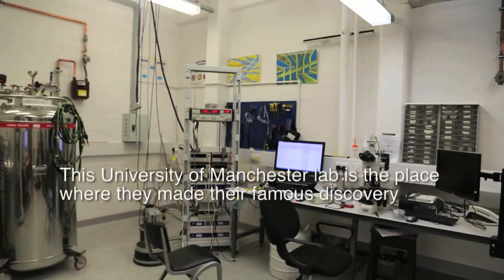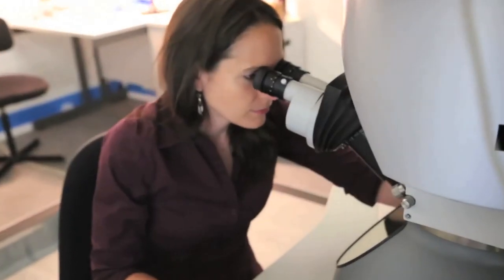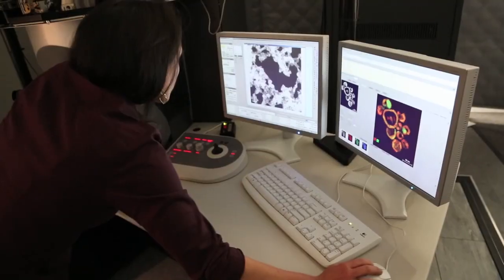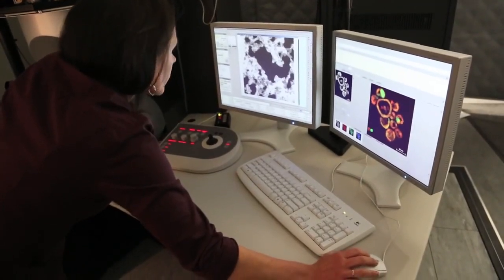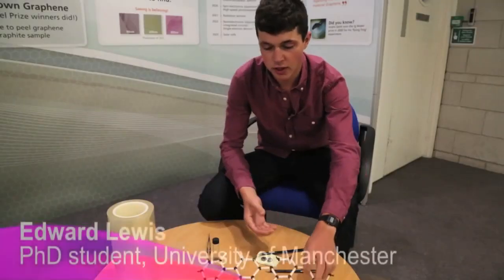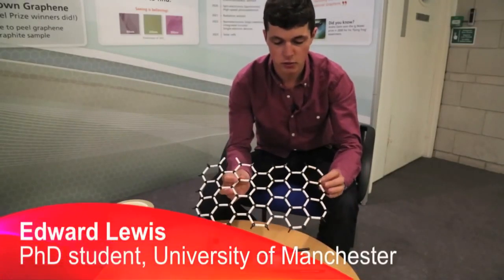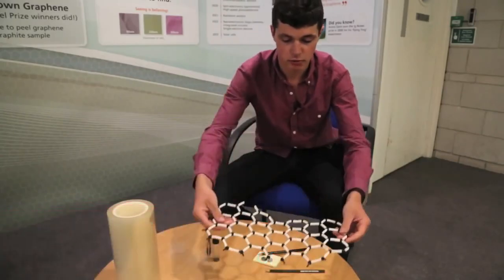Theory had shown that graphene wasn't possible to exist in nature, it wasn't stable, so many people didn't think to look for it as a true two-dimensional material. And André Geim and Kostya decided that this was not necessarily true, and so they went looking for it. And the way that they went looking for it was using, as you've probably heard of, the Scotch tape method, which involves sellotape and a piece of, not pencil, but of high purity graphite. How do we go from this layered material to getting a single layer? A layer that's only one atom thick, a layer of graphene.